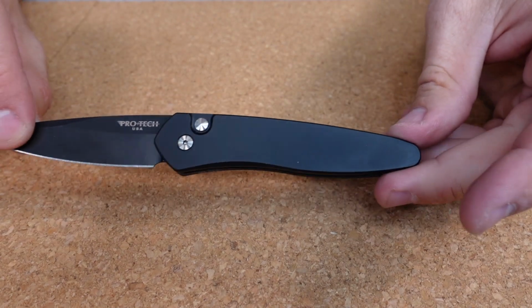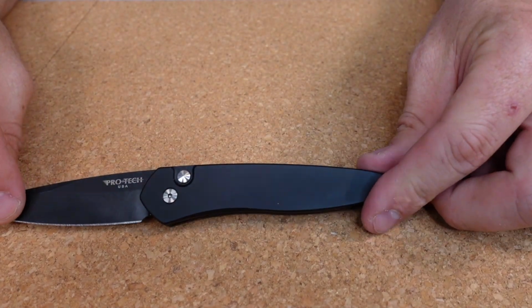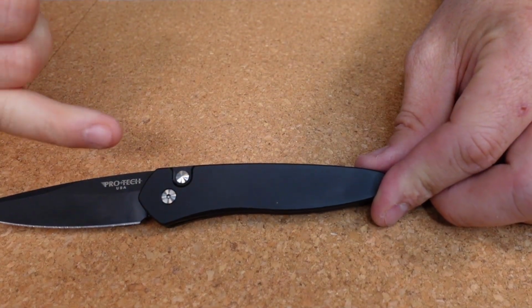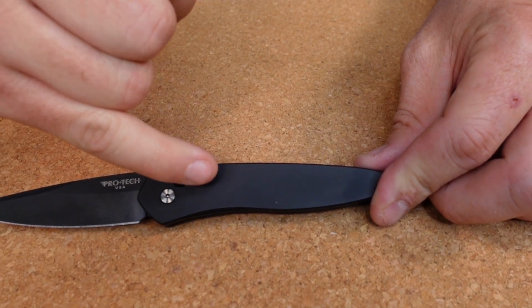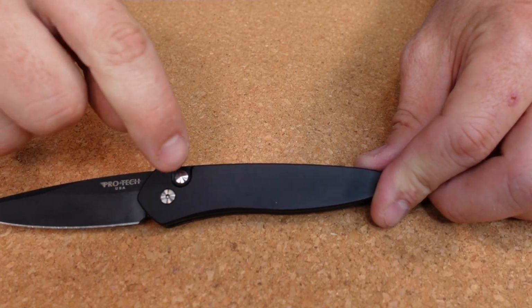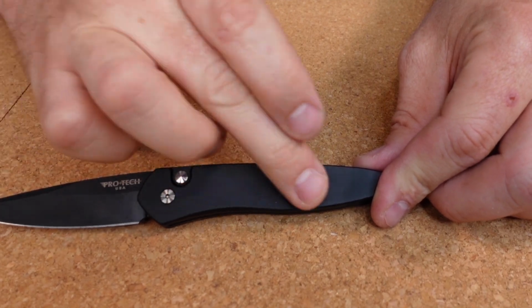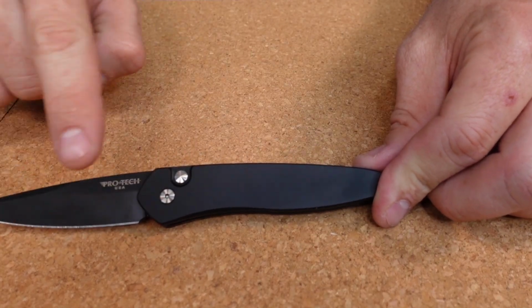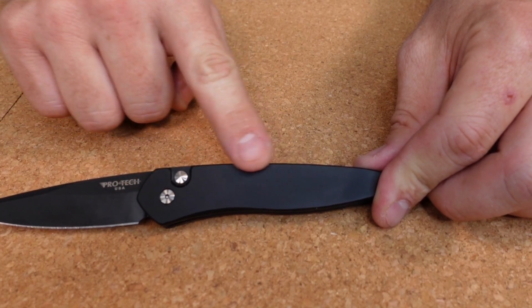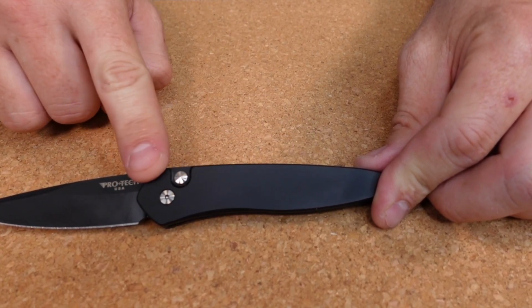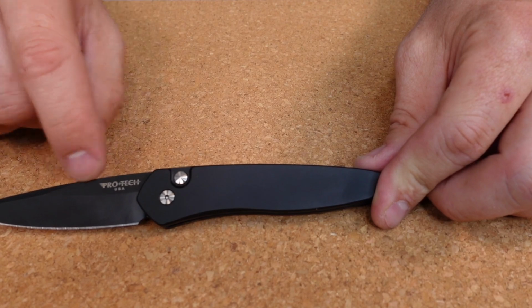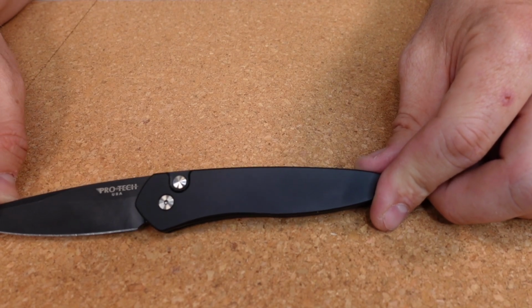Unfortunately, these knives can be scratched, or gouged rather, if you run into something that's actually hard enough to deform the layer beneath the coating. You can cut the aluminum beneath and leave yourself a bit of a gouge. But for most purposes, you can consider these knives to be scratch-free. Simply give them a good scrub, and any scuffs on the surface will probably come off and go away completely.